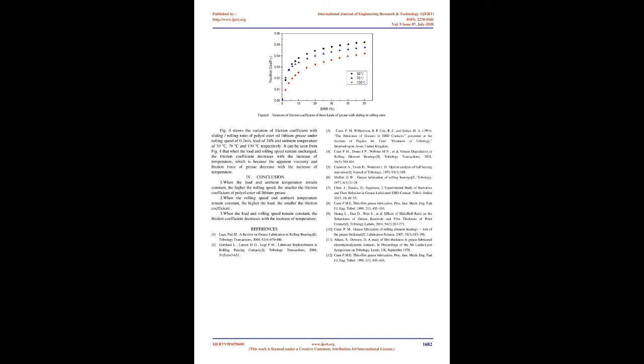1. When the load and ambient temperature remain constant, the higher the rolling speed, the smaller the friction coefficient of polyol ester oil lithium grease. 2. When the rolling speed and ambient temperature remain constant, the higher the load, the smaller the friction coefficient. 3. When the load and rolling speed remain constant, the friction coefficient decreases with the increase of temperature.